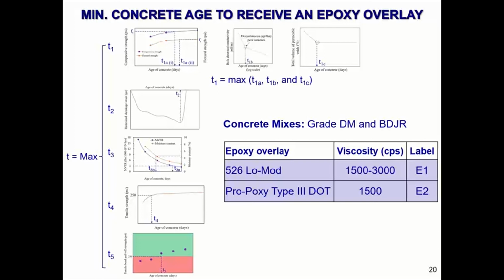T1 is the maximum wet curing duration for the concrete to either T1A, reach the flexural and compressive strength requirement that we have in our mix design, T1B, to develop a discontinuous pore structure within the concrete, or T1C, to develop total permeable voids to ensure concrete durability from air entrainment.